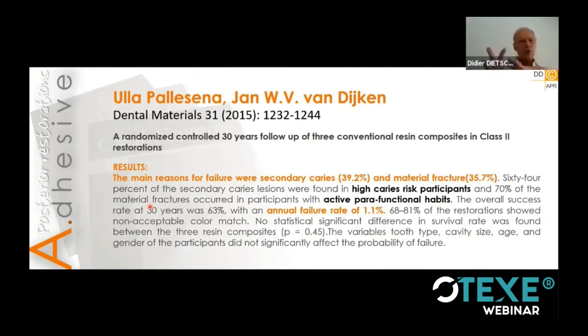I don't want to show you too many literature references, but here you see a randomized controlled study after 30 years made by a colleague from Sweden. And you see that over 30 years of function, we have only roughly 1% of annual failure rate, which is very, very small, actually. It's a very, very good performance.